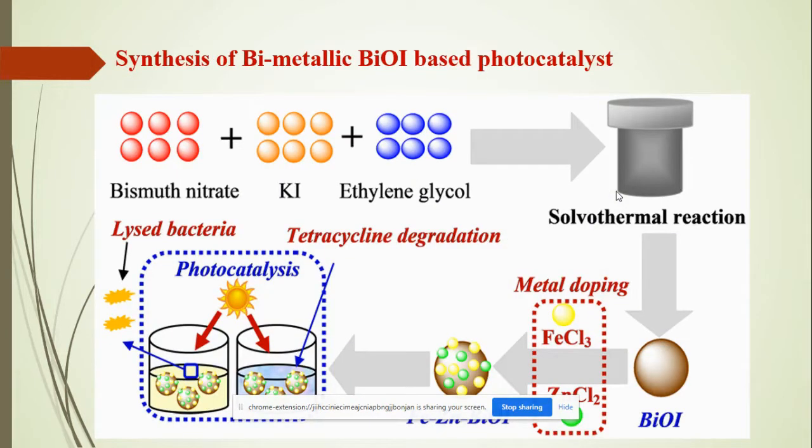So, how do we synthesize bismuth oxyiodide photocatalyst material? Synthesis involves the mixing of bismuth nitrate and KI salt in ethylene glycol, then kept under solvothermal reaction for 24 hours at 120 degrees centigrade. After that, we get spheres of bismuth oxyiodide, which are very porous.